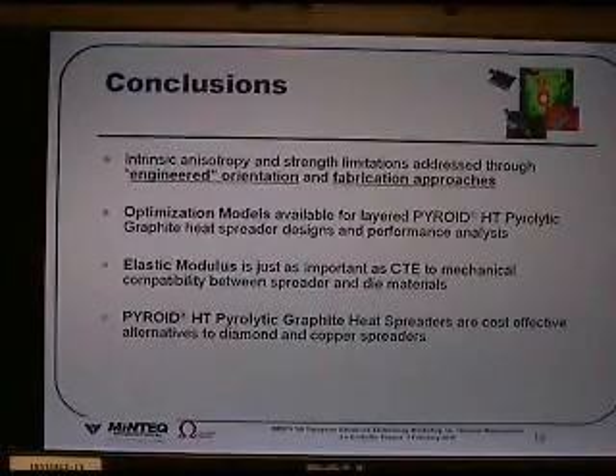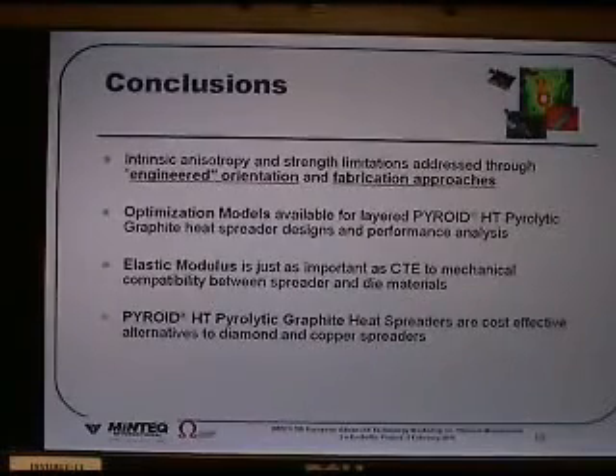So in conclusion, we believe that the intrinsic anisotropy and strength limitations have been addressed using an engineered orientation in the fabrication approaches with our Pyroid HT pyrolytic graphite. We've developed an optimization model which illustrates the effectiveness and efficiency of this material as a heat spreader. The elastic modulus, we've noted, is just as important as CTE for the mechanical compatibility between the spreader and the die materials. And finally, we hope to demonstrate for you that Pyroid HT pyrolytic graphite heat spreaders are a very cost-effective alternative to diamond and copper.